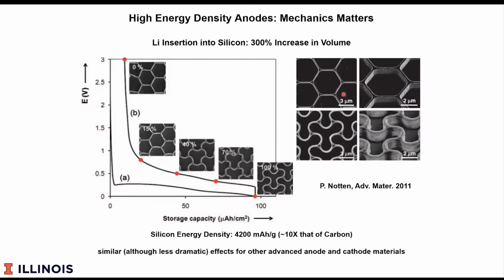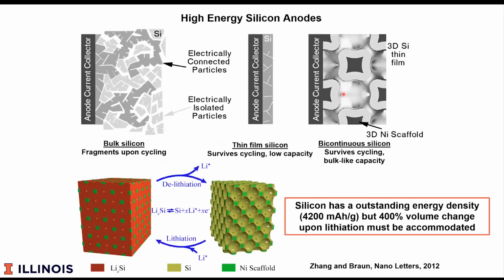And so a popular material is now silicon because of its high energy density. It's significantly more than that of carbon, but I'll show you silicon has a much more important advantage than just the energy difference. So a while ago, we also looked at using these three-dimensional structures for silicon, and now, unlike the cathode, here the three-dimensional structure is an advantage. The material, as it lithiates, swells and contracts, and so the scaffold enables this open structure, provides a space for the lithium to breathe, and that's quite important.